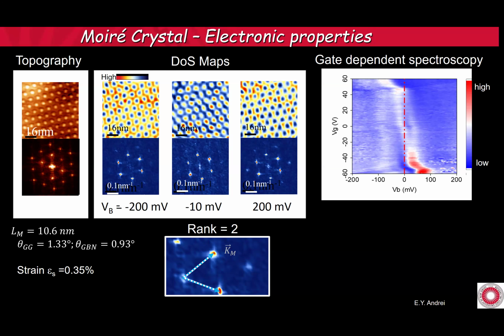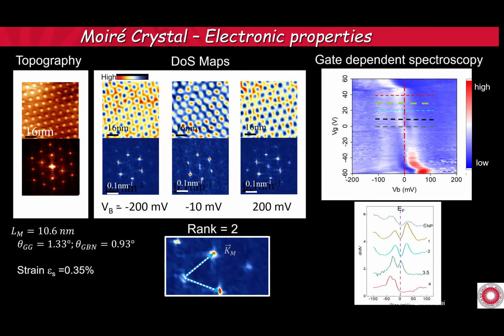and we could see that more clearly here. So these should be correlated gaps. We don't know what they are at this point. And it kind of looks very much like what you see in TBG that is not aligned to boron nitride. The big difference is that it is very far from the remote band. The remote band in TBG is at kind of 20, 40 millivolts away, and the remote band here is very far away. So the alignment has done something to the band structure.